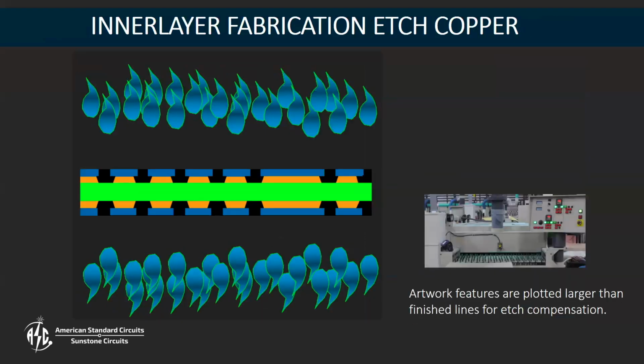All right, so then we go through and etch. So we expose that panel now to an etching solution. Two common ones are cupric chloride or an ammoniacal etchant. There's pluses and minuses to both. Usually with inner layers, the cupric chloride gives you a little bit better etch factor and a little bit straighter sidewalls. But in general, as you're etching down from the top down, the top of the trace underneath the photoresist will be exposed to that etching material a little bit longer than the bottom of the trace. So in general, you'll get kind of a trapezoidal shape to your etched traces.